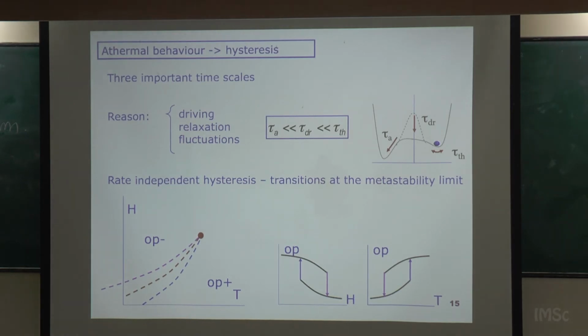Then there is the time that it takes the system, if it reaches the maximum, to relax and fall into the minimum. This is what we call the relaxation time, or I will call it the avalanche time. It is the typical time for relaxing from an unstable situation to a stable situation, very fast typically. But then there is another question: we are driving the system externally. The driving is changing the barrier.